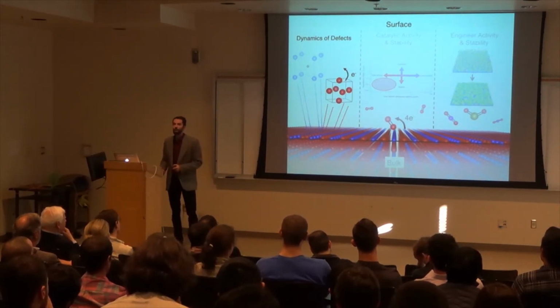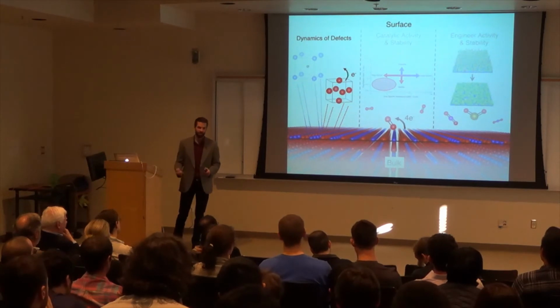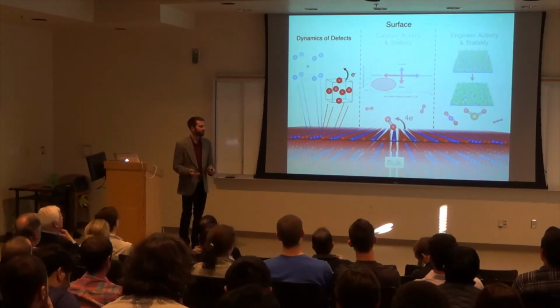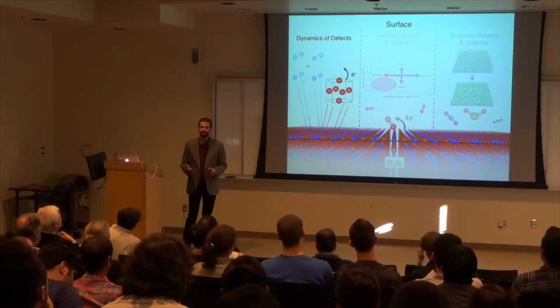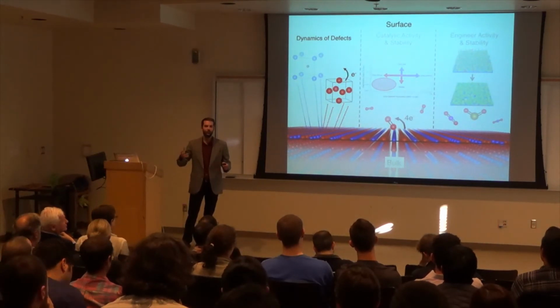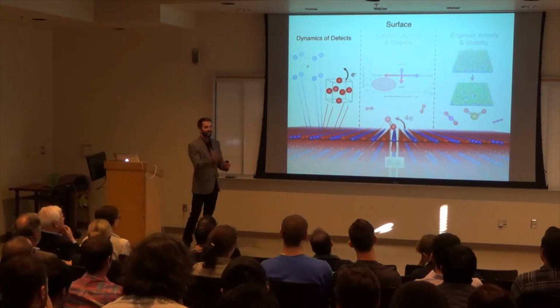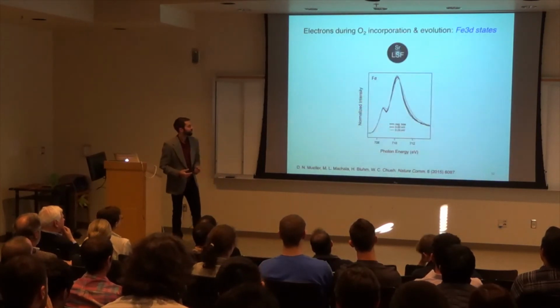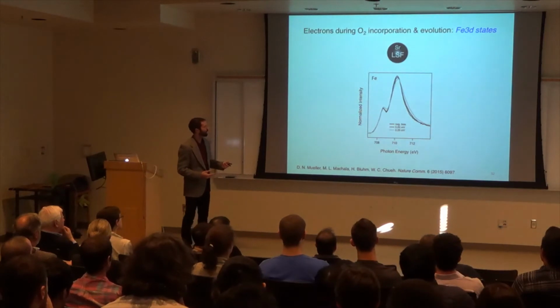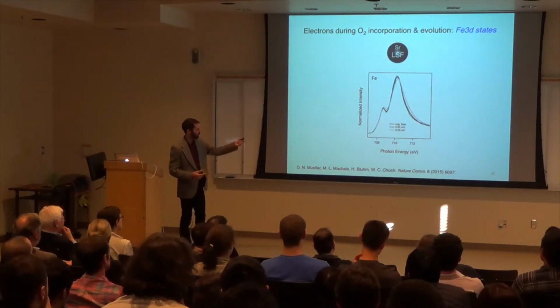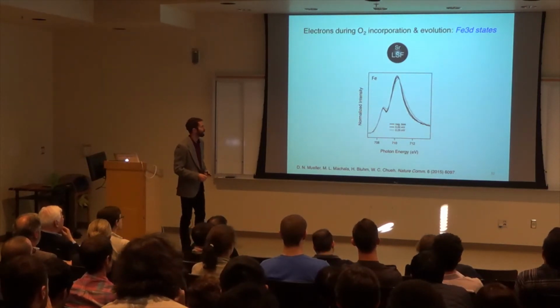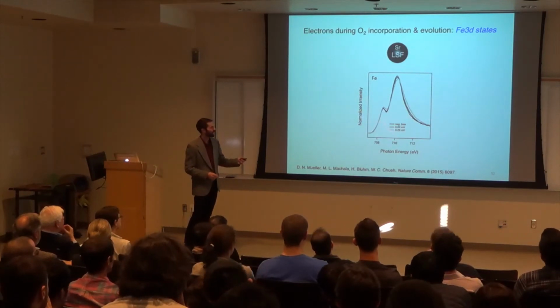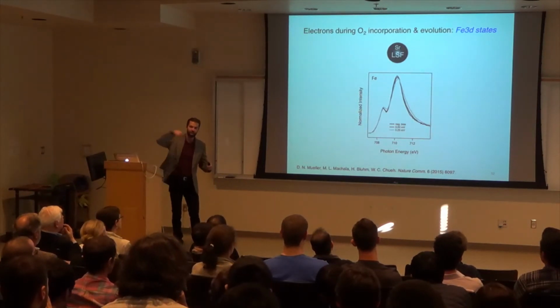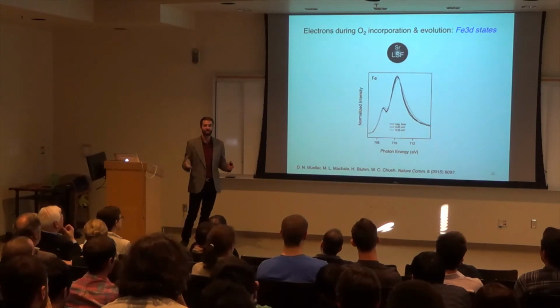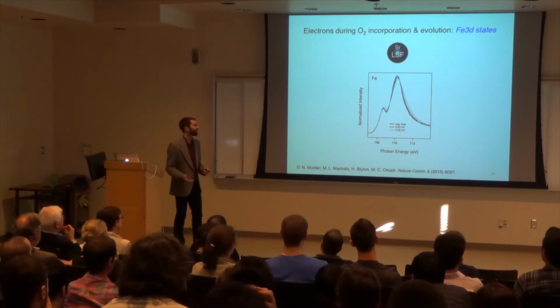And for this, we turn to X-ray absorption spectroscopy, and I'm going to show you a spectrum of what that is. To actually see what a reaction is doing in real time, we're going to apply a bias, a voltage, to the sample to drive oxygen into the material and out. Okay? So this is what one of those spectra looks like. We have the intensity on the y-axis as a function of photon energy on the x-axis. Right here, overlaid over each other, are different voltages, different biases, trying to drive the oxygen in and out to see if we're going to change the oxidation state of the iron.